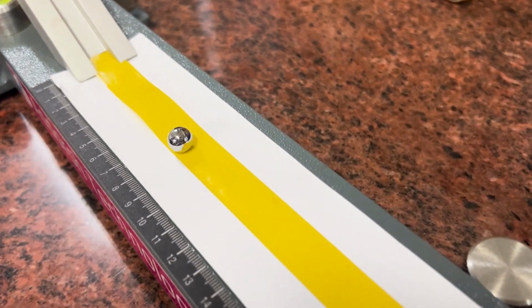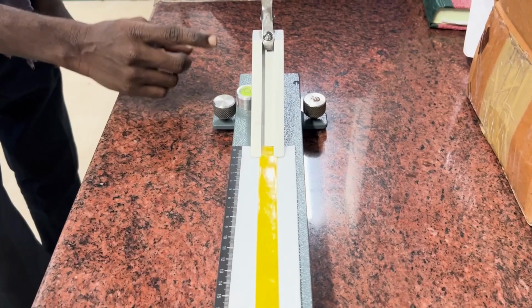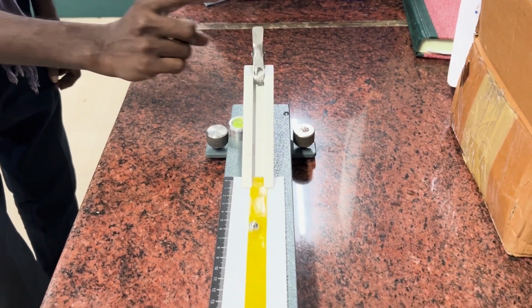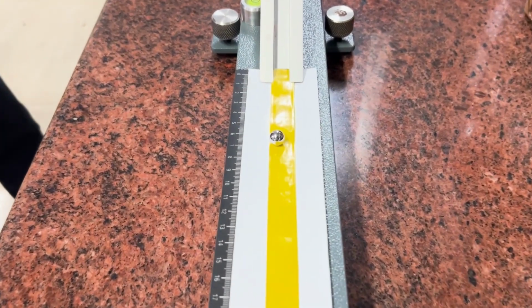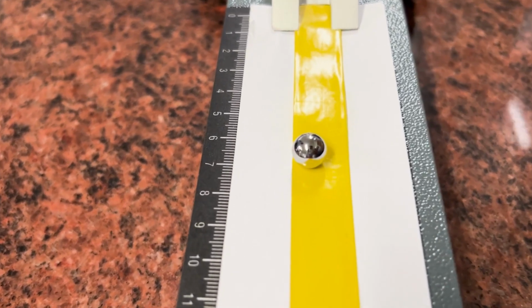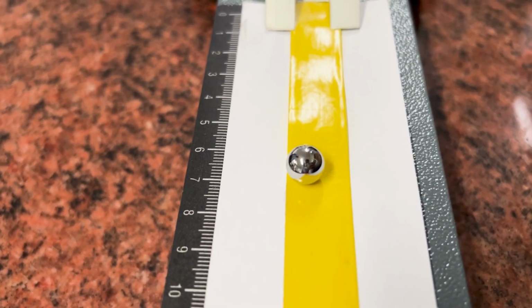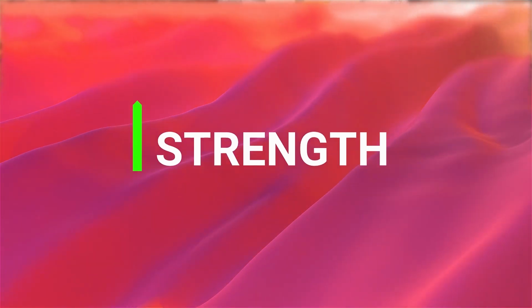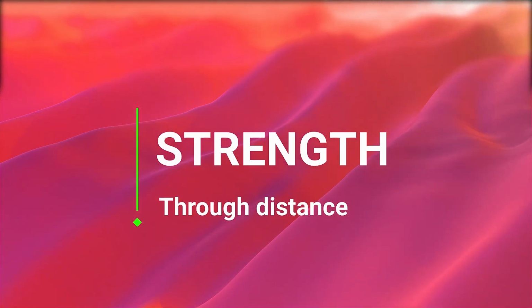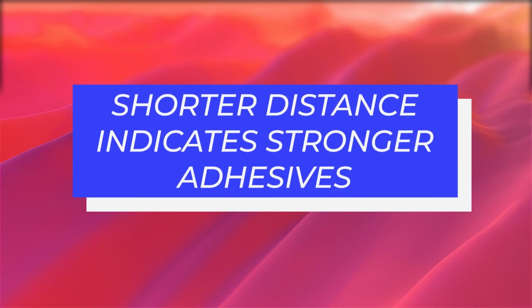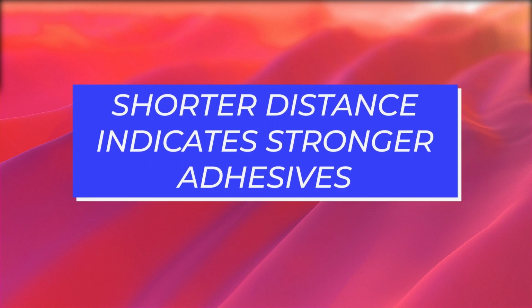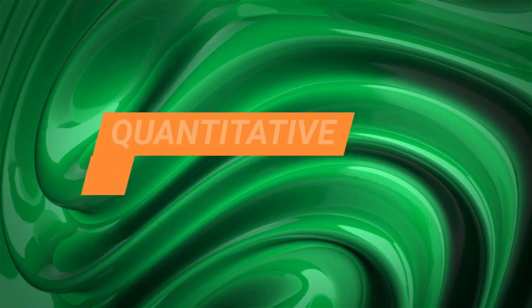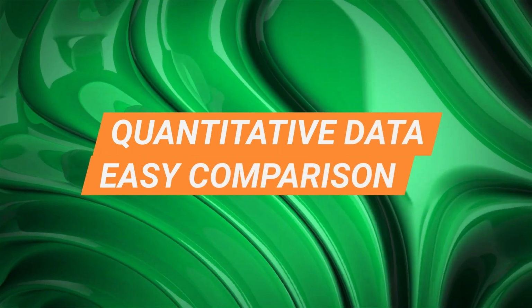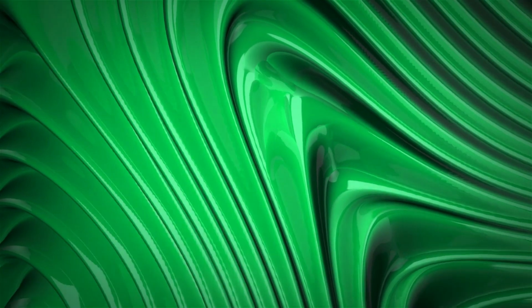Next, a steel ball bearing of defined weight and diameter is released down the slope of the inclined plane from a standard height and distance from the tape sample. As the steel ball rolls down and makes contact with the tape surface, the quantitative measurement taken is the distance the ball travels along the tape from the point of initial contact to where it completely stops sticking. This measured rolling ball tack distance directly correlates to strength of adhesion. Short tack distances indicate more aggressive, pressure-sensitive adhesives while longer distances equal non-aggressive adhesives with poorer tack. This test provides quantitative adhesion data that allows precise comparisons between different tape adhesives rather than subjective assessments.